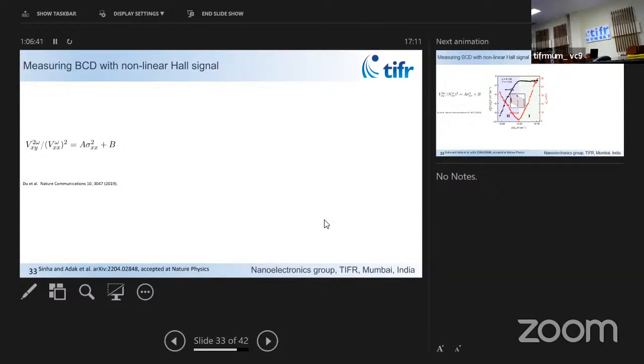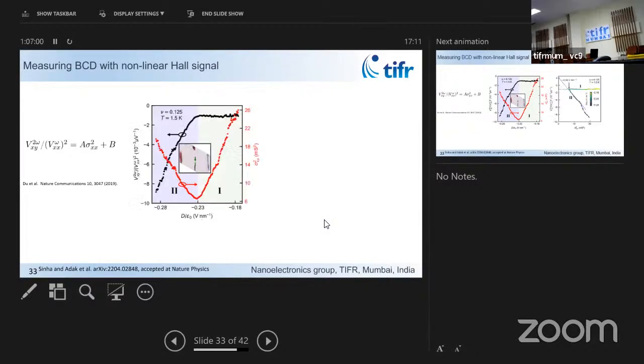You measure the experiment and then you do the scaling analysis. Okay, so this is the Hall signal magnitude normalized with square of the nonlinear voltage. It gives you this kind of scaling relation, and this B is a measure of the Berry curvature dipole, and that's sort of what we did. So we measured this property, V2 omega xy, divided by this, as a function of electric field, and we also measure sigma xx squared, which is this quantity, and then we do a parametric plot.